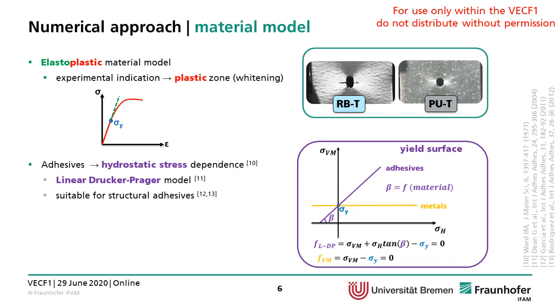Regarding now the numerical approach for the simulation, we used an elastoplastic material model. We use this due to experimental indication of a plastic zone, so whitening, as you see here in the quasi-static test, the presence of whitening of both types of samples. And we use a linear Drucker Prager model for the material, since adhesives show hydrostatic stress dependence in their yielding behavior, and many studies have shown that this is a suitable approach for structural adhesives. So if you compare with the von Mises material model, you can see here, by plotting the hydrostatic pressure, hydrostatic stress and the von Mises stress, the difference between the linear Drucker Prager model and a von Mises material model.